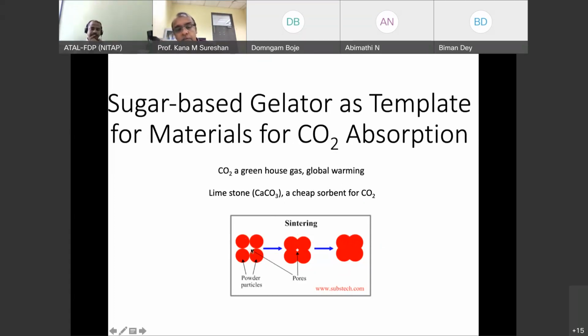The problem is, after a few cycles of heating and cooling, this becomes amorphous, not crystalline, and there are not enough pores. So this process becomes inefficient. Only the surface activation happens. That means only the calcium oxide on the surface of the material will become calcium carbonate. Most of the calcium oxide inside will remain calcium oxide as such. This process is called sintering, and this is bad.